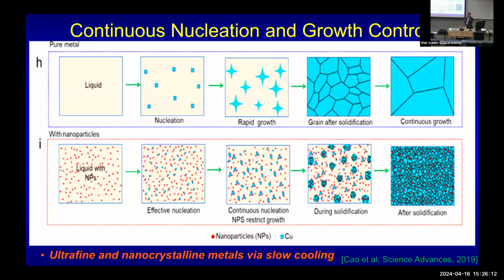Traditional methodology is one shot: once I nucleate, I grow very quickly and occupy as much space as possible. That's exactly why we couldn't get small grains, unless you use rapid cooling and everything. But with this technology, we can use a very slow cooling rate because the nanoparticles do the work. They pin you down and continuously block you, and we can get very small grains.